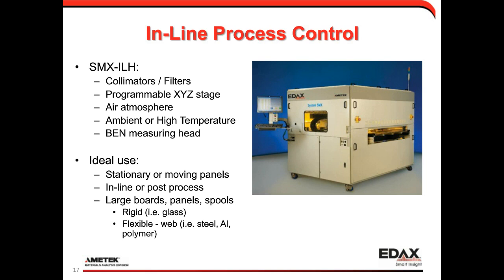The size of these systems can be customized. We've built them relatively small, and we've built them to handle samples with widths up to a couple of meters. So that's a bit of flexibility we have in whatever it is you're trying to measure. The kinds of systems we're showing here handle moving panels on a conveyor. We also can take the measuring head and build it into a vacuum deposition system. We can put a bucket into the vacuum deposition system with X-ray transparent windows in that bucket, put the measuring head in there, and we can make measurements through the X-ray transparent windows.